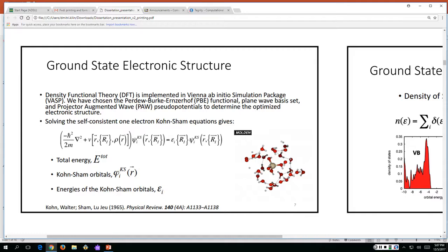And so because we were looking solely at the gamma point, and we knew that the band gap energy didn't match up with that of experiment, the absorption energies shown on the top also show absorption onset at a much higher energy than we would expect. They correspond with the calculations, but not with experiment. So again, to introduce the concept that multiple K points are necessary for the correct electronic spectra, the bottom four right panels show K point corrections for the vacancy and the charge-corrected state. And so here, the top two have the total absorption spectra, which have their onsets at 800 to 900, which is ideally what we would want to see, with the bottom two panels showing the individual contributions to absorption by each single K point calculated for the system.